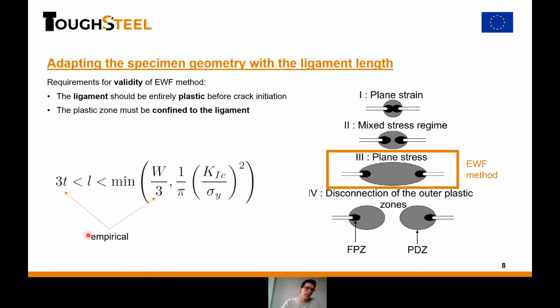And so what you find in the literature is some bounds on your ligament length. Typically you see the lower bound to be between 3 to 5 times the thickness, and the upper bound is either linked to the width of your specimen, typically a third of the width or half of the width, or the size of the plastic zone, computed with the Irwin formula, but you also need to know some material parameters. But one thing to note is that these two are empirical values and they are not very well defined, so the bounds are a bit fuzzy depending on which material you use. But we can still take advantage of this.